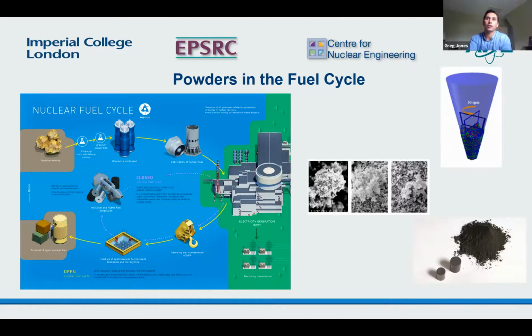You can see in the top right here, we've got a conical stirrer of MOX powder. This is plutonium mixed with uranium, and it's mixed in this stirrer in a dry mix to get a homogeneous mixture before MOX pellets are formed. This tends to be moderated by a hydrogenous material. There's a criticality safety case where a hole in the stirrer causes hydrogenous material to enter the stirrer, which can lead to a nuclear criticality excursion.